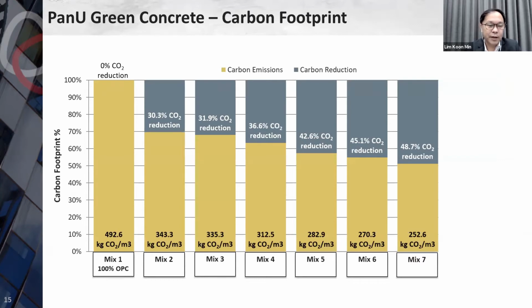Now, let us take a closer look at the carbon footprint reduction that we have for PanU green concrete. Mix 1 is typically 100% OPC concrete with no recycled materials, no green cement whatsoever. For typical grade 40 concrete, the carbon footprint we are looking at is about 492. Between mix 2 to mix 7, we have different types of green materials added to replace the natural aggregates and even the ordinary Portland cement. So we are able to reduce the embodied carbon, upfront carbon, by as much as 48.7%.